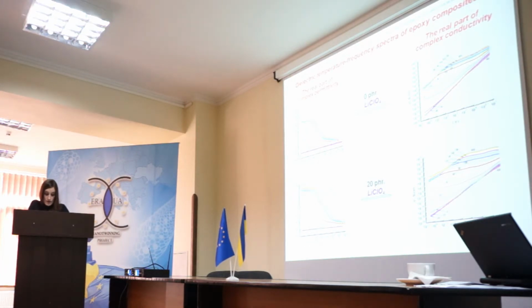At temperatures higher than the glass transition temperature, softening of the polymer chains occurs, which leads to the release of lithium cations and to the growth of permittivity values. Free lithium cations pass into the conduction band and begin to move along the polymer chain with the participation of oxygen atoms in this movement. This charge transfer leads to an increase in the electrical conductivity of the system and the appearance of a plateau at low frequency. The so-called plateau of DC conductivity is a range where conductivity values do not depend on frequency in the spectrum of the real part of the complex conductivity.